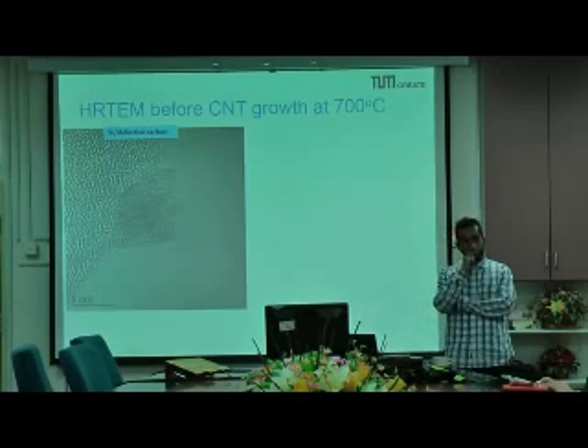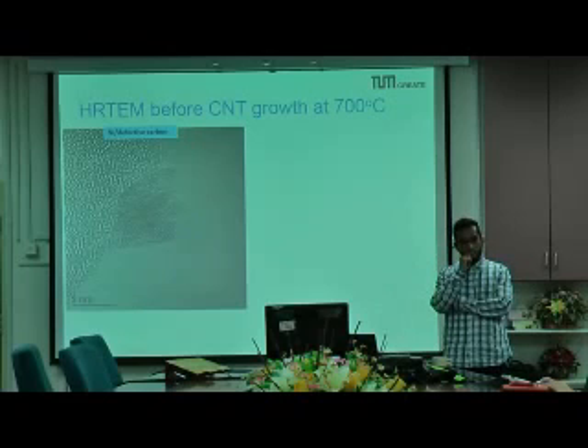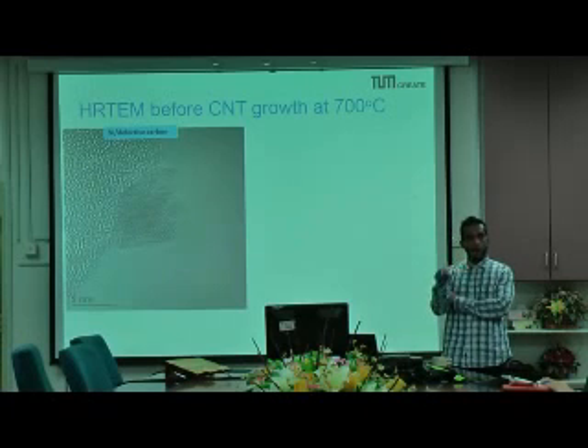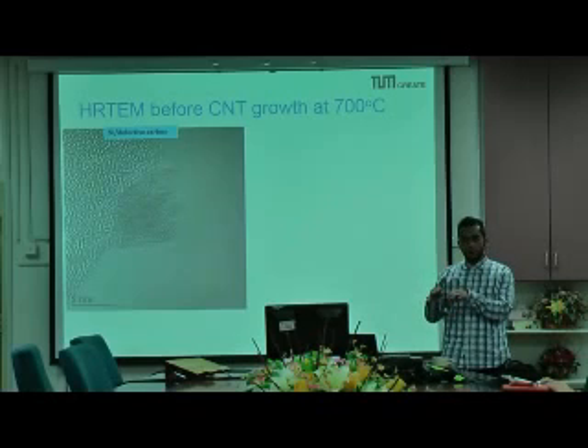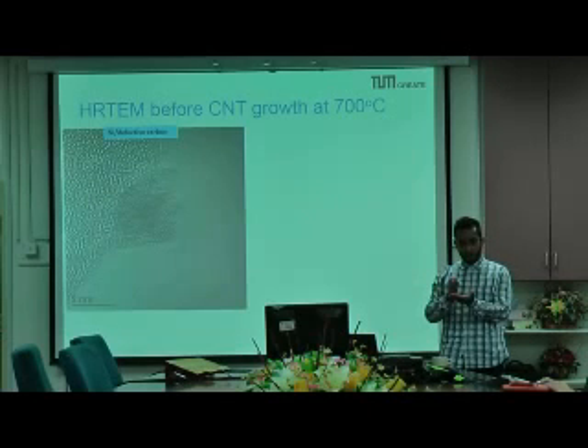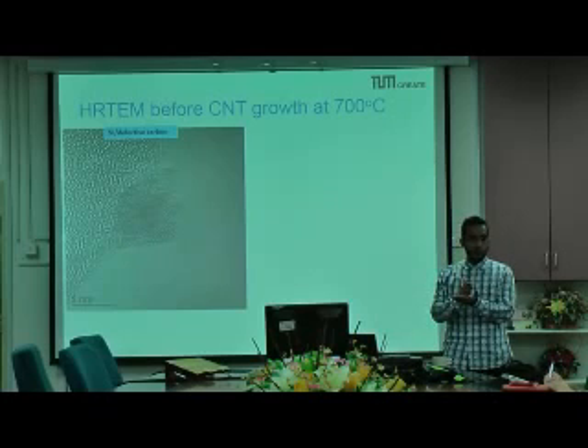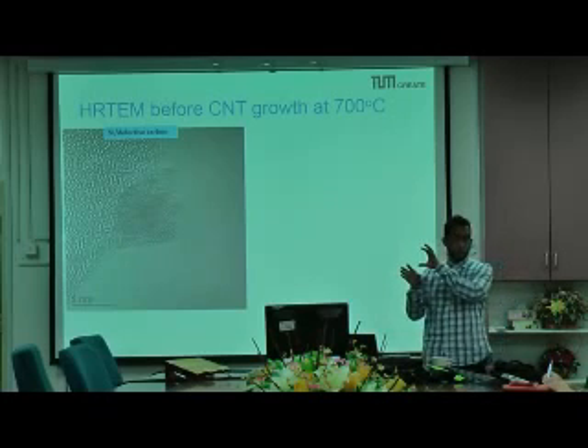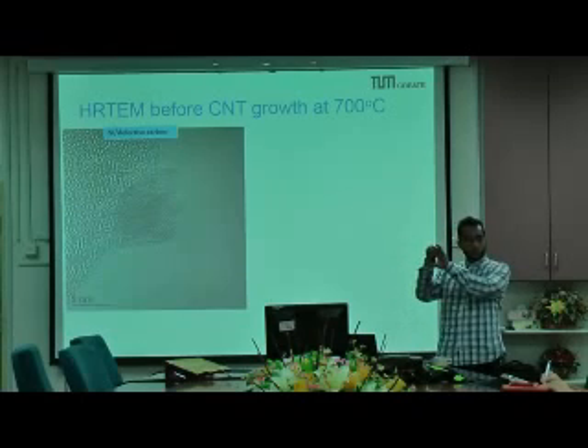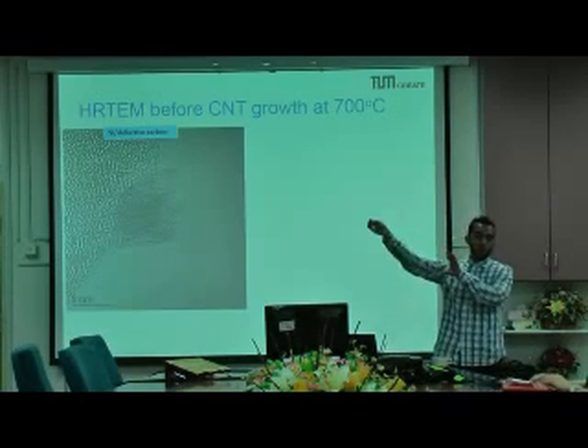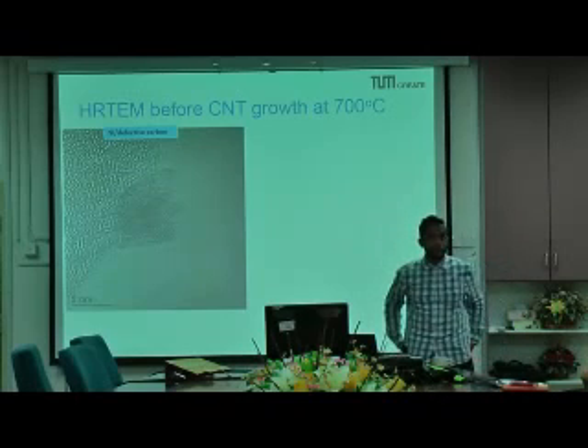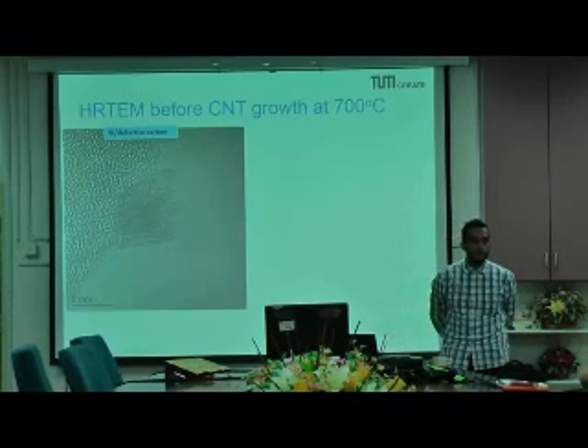Yes. So for example, with the treatment, do you improve the amount of the CNT, or improve the time, to get longer growth? Yeah. The experiments were done at 5 minutes of growth time. I don't want it to be too long, so that you lose the attachment between the nickel and the carbon support. I want to have an image to justify that the growth is coming from the nanotube. If it's growing too long, then it can. What is the effect of this carbon support when you have this?